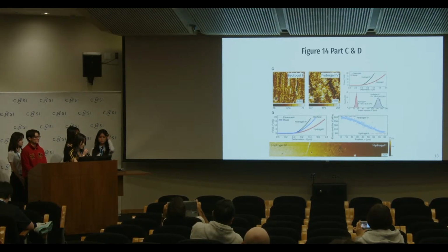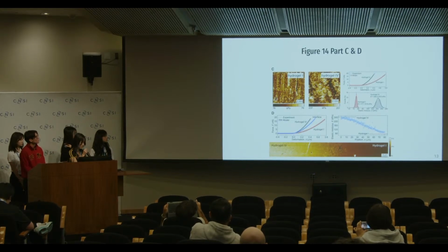The graph on the right shows a transition across a spatial region. Moving from hydrogel 4 to 1 shows a sharp drop in stiffness, illustrating a well-defined interface between the two hydrogels. The one at the very bottom shows a transition from high stiffness, which is hydrogel 4, to low stiffness, hydrogel 1.